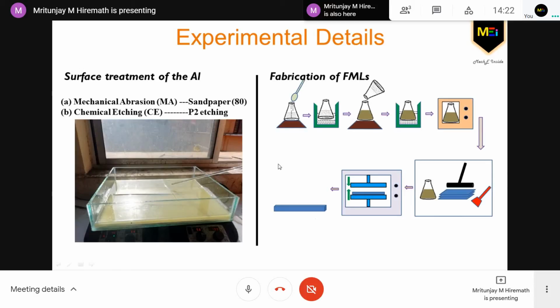The next step was to fabricate the fiber metal laminate. This process indicates how the nanofiller is processed in order to mix it with the epoxy matrix, and the whole constituent is used as a matrix. Once the matrix was ready, the composite was fabricated by preparing the aluminium, by stacking the aluminium and the matrix.